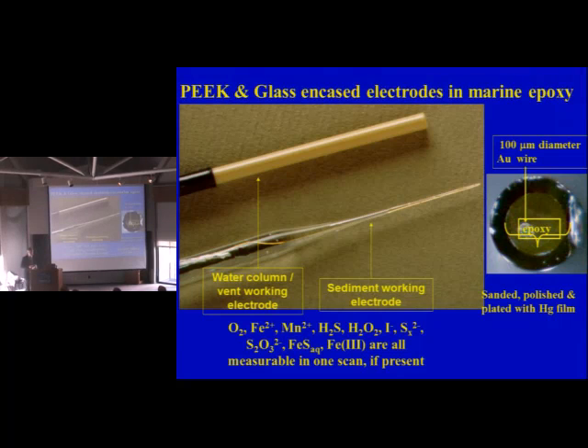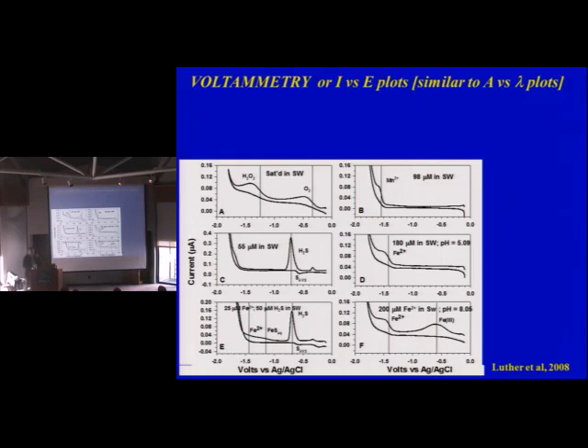We've actually tested this design to about 5,000 meters, 500 bar, and up to 120 degrees C. It turns out the epoxy starts to melt, or at least gets soft at 100, which makes it tough. We've tried PEEK. We've done some injection molding for the PEEK, and the PEEK doesn't start to get deformed until about 250. So we can actually go higher, but we haven't done that. So I wanted to show you some scans.